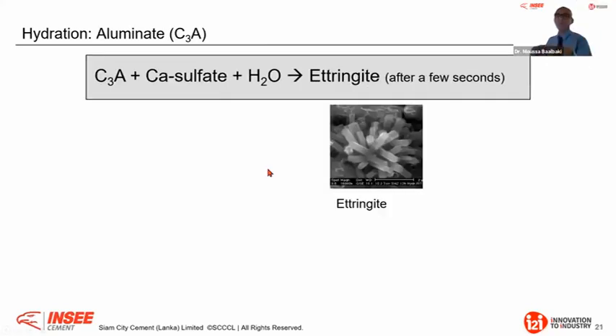Now, when it comes to aluminate, the aluminate needs to be regulated with calcium sulfate. Otherwise, you have what we call a problem with stiffening, or sometimes false set. This is really coming from a poorly regulated C3A.